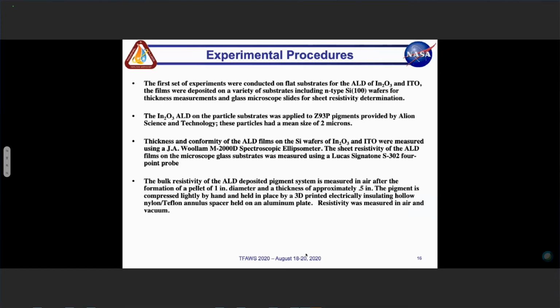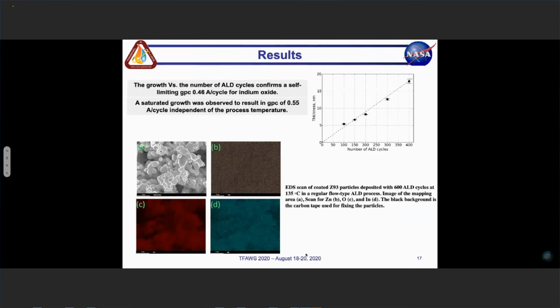So in terms of experimental procedures, we loaded a pre-weighed amount of pigment within our basket. We then rotated the basket at X revolutions per minute. Then we also had a dummy silicon wafer and a glass slide as well. And we went through the indium oxide, tin oxide process, and we did spectrometry and 4-point probe measurements in order to determine how well the charge bleeds off, or the resistivity that we had across our film structure.